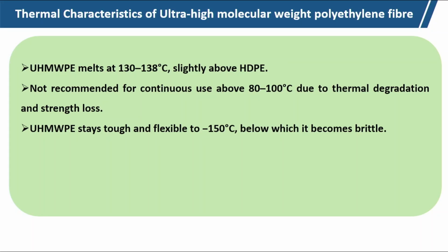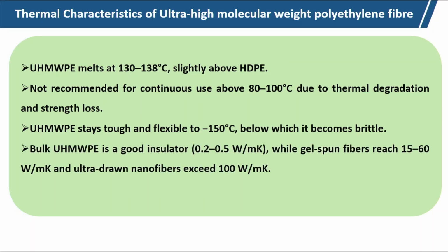So, these fibers stay tough and flexible down to minus 150 degrees Celsius. So, for low temperature or normal temperature applications, this is an excellent fiber, but below minus 150 degrees Celsius it becomes brittle. Normally, in most environmental conditions we do not reach that stage in practical application.